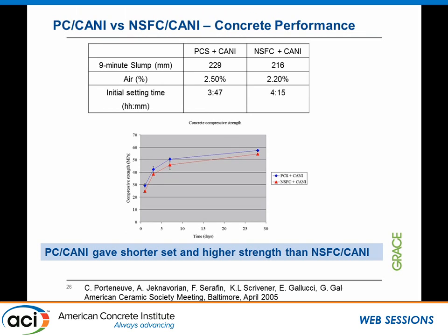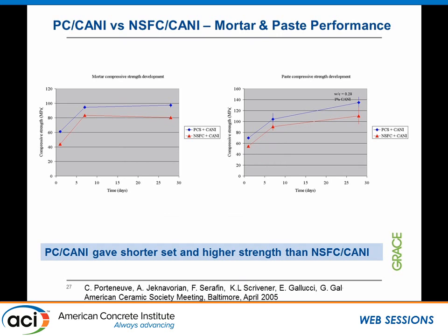What we see in here is really, for this mix design on the concrete, we see with the polycarboxylate with calcium nitrite a decrease or faster initial set time, and also a better strength development. The blue curve is the one that has the polycarboxylate. When we're dealing with the mortar and paste, once again, we do see the higher strength in the mortar with the polycarboxylate and higher strength with the paste. This really is just to show you the system that we're using when we're looking at something mechanistically in the mortar or paste, that it would reflect that same level of strength gain for the mix design.